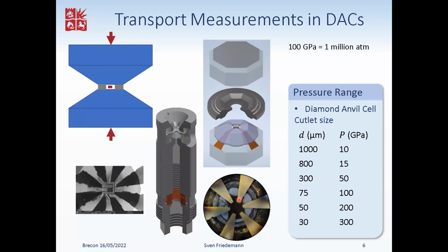So you can see these gold electrodes coming in from 6 directions, and then silver paint or other conductive methods can be used to make contact between the electrodes and the sample at the inside of the pressure cell. The outer bit of the electrode is freely accessible, so you can attach a standard wire to that and hence use those electrodes to inject current and detect voltages, for instance, for resistance measurements, magnetoresistance, Hall effect measurements, any electrical transport measurement that you could imagine.